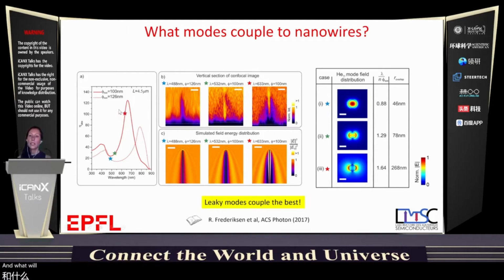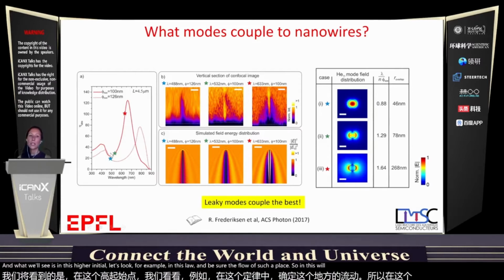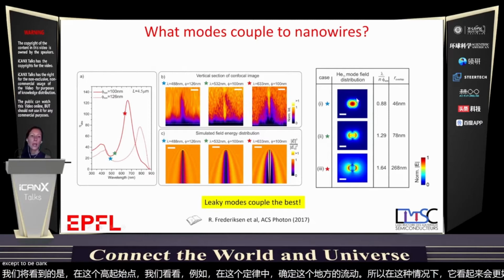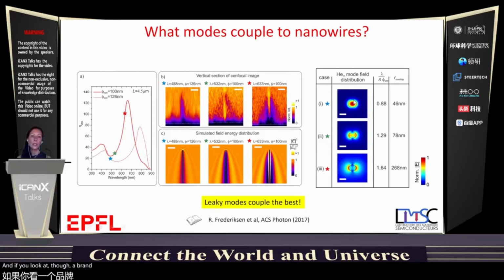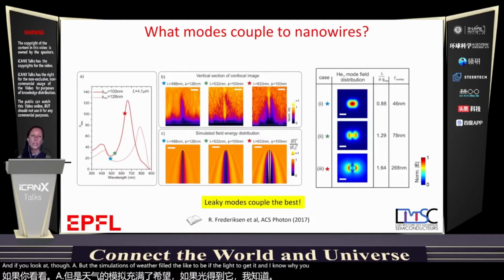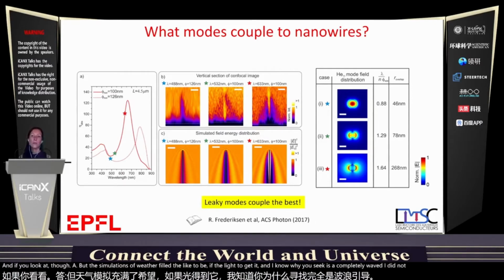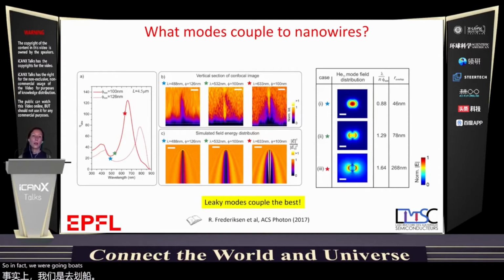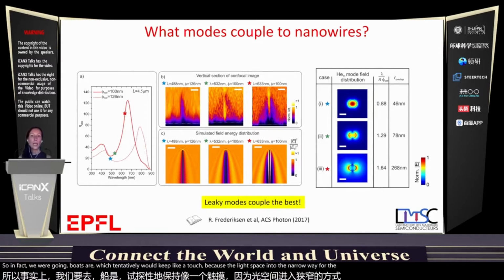And what we'll see, let's look, for example, at these low absorption cases. If we look where the light is, we see that there is no shadow developing here. In fact, the nanowire is absolutely dark. And if we look at the simulations of where the light would be, if the light would get into the nanowire, you see this as completely wave-guiding mode. So in fact, wave-guiding modes, which intuitively would give light absorption because the light stays in the nanowire for a long time, in fact give you very low light absorption.